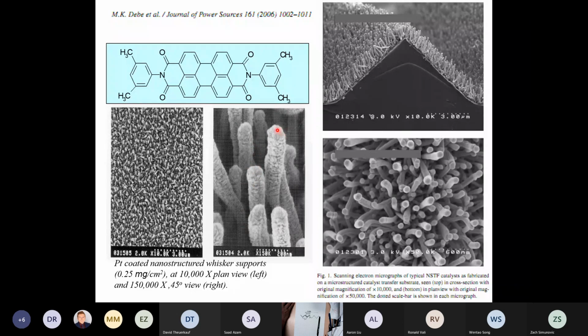So here you see the whiskers, they're more heavily coated at the top, but as you go down, you still have whiskerettes on them near the bottom. They kind of look like a baseball bat once they're coated. One end is pretty thick, and the other end, which would be the handle of the baseball bat, you can see it down here, it's not coated as well. But it coats pretty uniformly over 3/4 of a micron, and that was good enough. So it was pretty impressive that it worked so well.